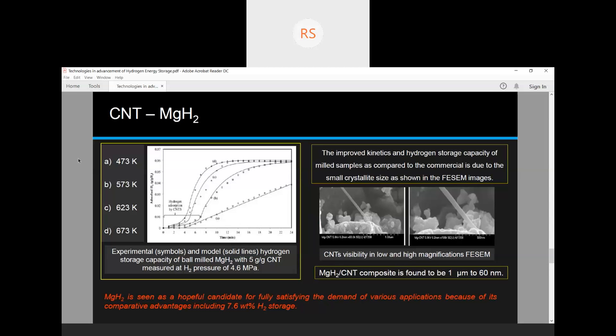This indicates that CNT may facilitate hydrogen diffusion in magnesium from magnesium hydrides. In particular, at 473 Kelvin, the hydrogen absorption increases drastically compared to the milled magnesium hydride or the pristine magnesium hydride. This indicates that magnesium and carbon interaction could provide enough hydrogen dissociation and diffusion sites. So hydrogen diffusion becomes a predominant factor at lower temperature. Therefore, carbon nanotubes play an important role as a tubular structure for easier hydrogen transportation inside the system.